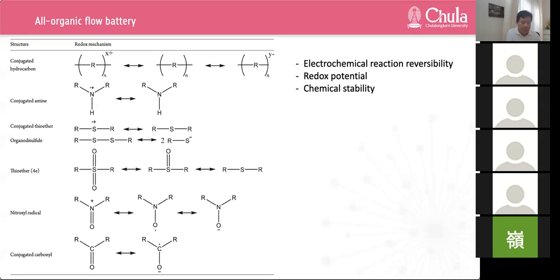Some basic requirements for these organic candidates include the following factors. The first factor is electrochemical reaction reversibility. This factor can determine cell polarization. Nitroxyl radicals present the highest reaction kinetics. On the contrary, organodisulfide and thioether show slow reaction kinetics because the bond breaking and forming of the S-S and S-O, right, which is a double bond, requires a high activation energy.